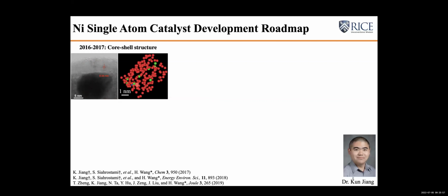By using a lot of sophisticated characterization tools, because in this case, we cannot use the traditionally used X-ray absorption spectroscopy to differentiate the nickel-nickel bond versus the nickel-nitrogen or nickel-carbon bond. The bonding distance is different, but because these nickel nanoparticles are always embedded in your materials and cannot be leached out, suggesting the very tight surrounding of these graphene shells. And eventually we utilized atom probe tomography that provided a very direct piece of evidence to show that there are a lot of isolated nickel dopants in the graphene shell region. So suggesting that these could be the active sites for CO2 reduction to CO.